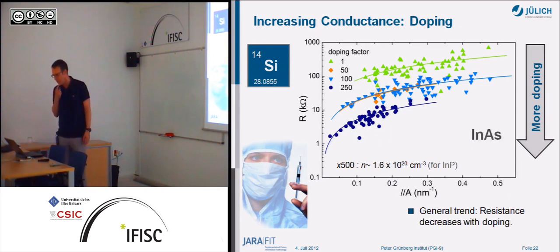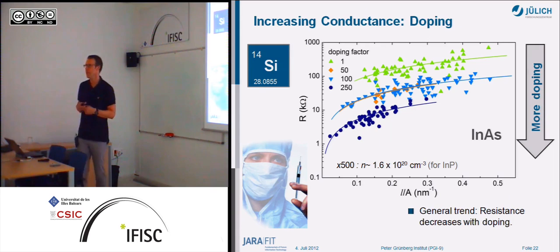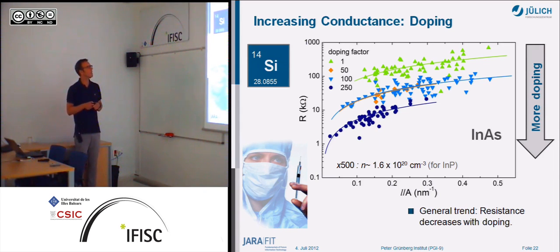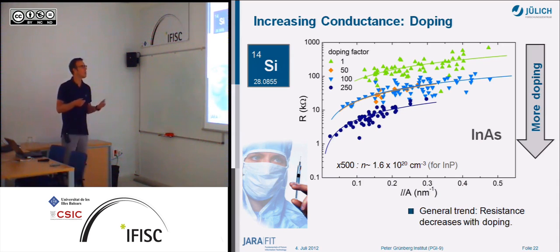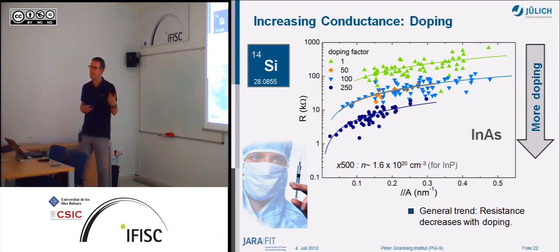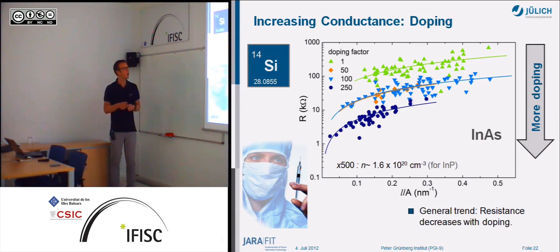What is one specialty in our institute is that we can even dope the nanowires, that we can increase the conductance of the nanowires by putting some silicon into the indium arsenide here. And you can see here, we call that doping factor 1 because we don't know exactly how to quantify how efficient the doping is. We can just say how much we put into the gas here. So this is doping factor 1. We have a large resistance here, and here we have doping factor 250, so 250 times the doping we have here. And you see that we can decrease the resistance of the nanowires by 2 orders of magnitude here.